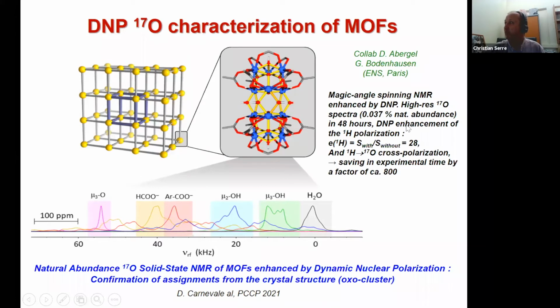they used the DNP to increase the NMR signal by a factor of 28, in order to collect in 48 hours the signature of the 17O oxygen of the material without any enrichment. And you can see here the signature of all the oxygen sites, validated by calculation, and they could clearly identify the ones of the two oxo clusters, especially this mu2-OH from the Zr12 cluster. They calculated the saving in experimental time to be a factor of 800, so that was very, very high. So it confirmed the structural model from the other techniques, especially the crystal structure.